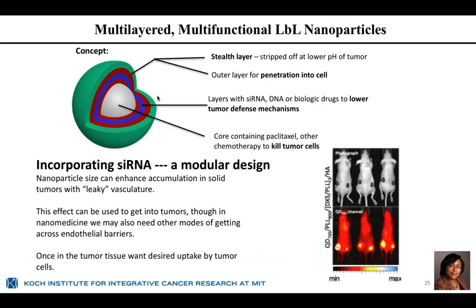So there's a lot of engineering design that goes into this approach, and we also rely on several mechanisms to get our nanoparticle through the bloodstream and into the tumor. And one of them is simply the use of size. It turns out that for a number of tumors, especially at the early and moderate stages of tumor growth, a lot of vasculature is created rapidly, and that vasculature will tend to have defects in it. There's a general belief that this leakiness of the vasculature will allow nanoparticles that are going through the bloodstream to leak into the tumor when they reach the tumor blood vessels.